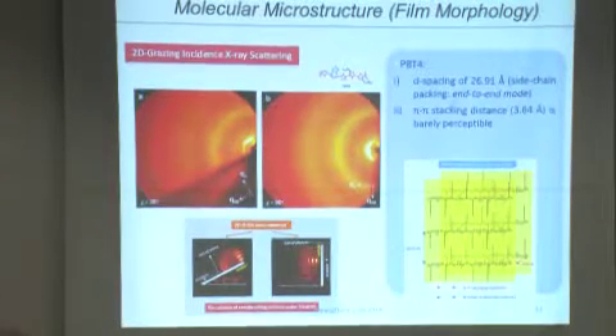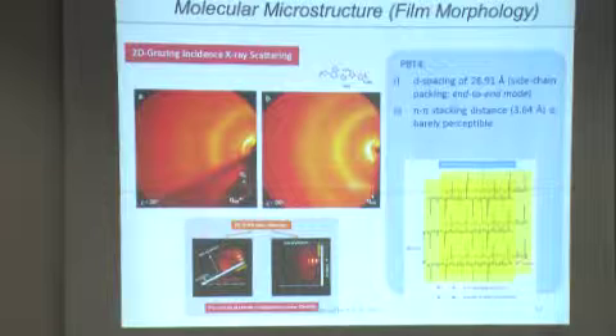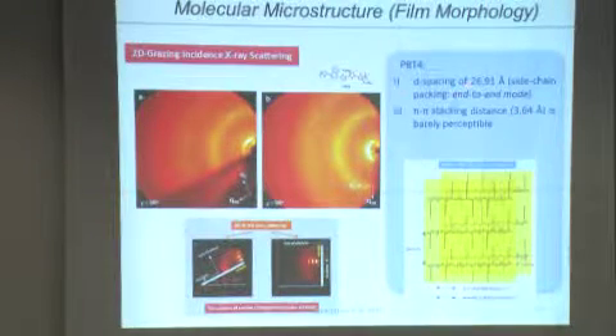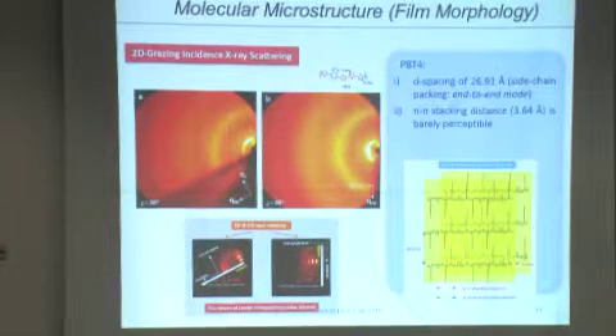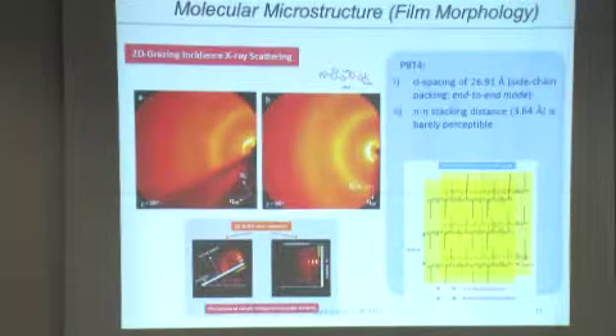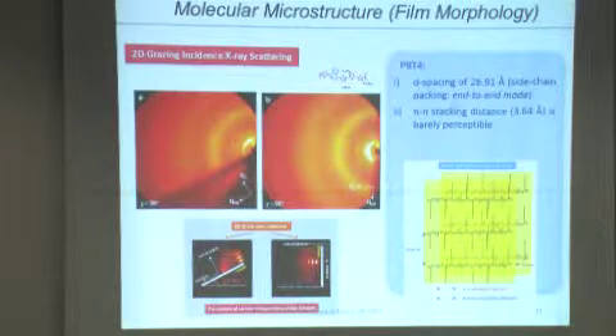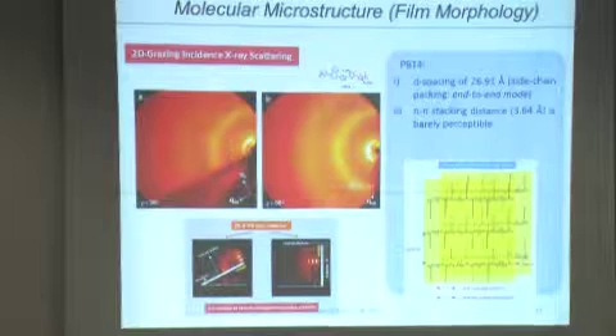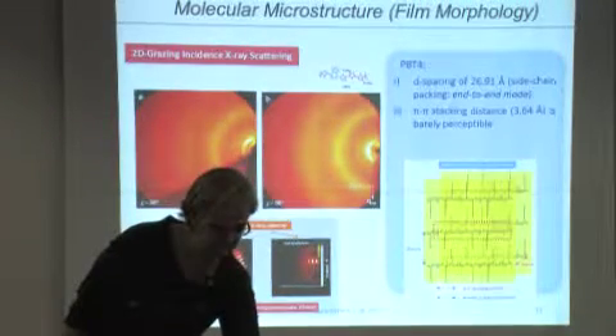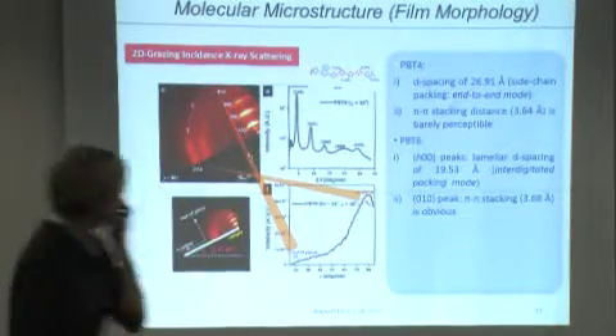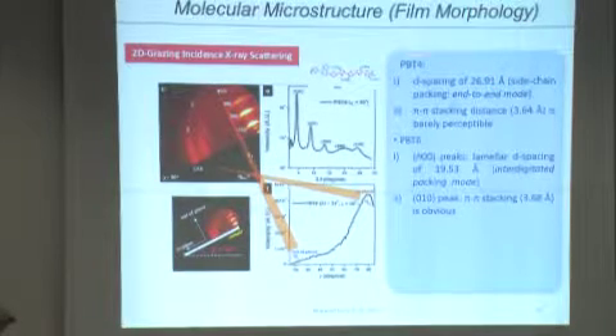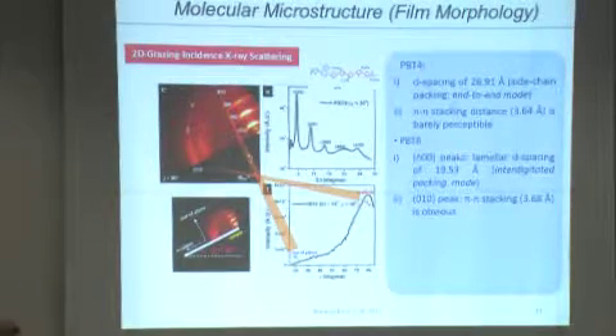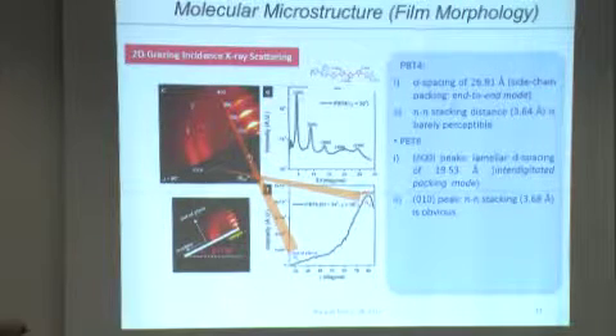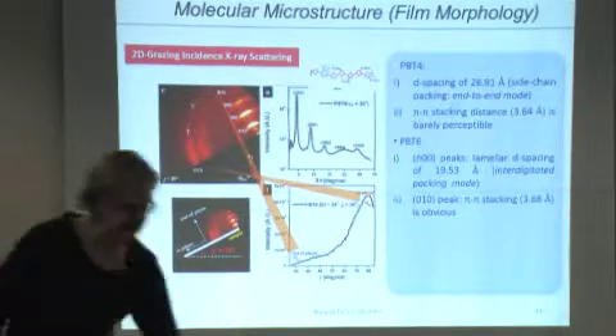The films themselves are fairly highly crystalline. There's a d-spacing of almost 27 angstroms, which indicates that the side chain packing is in an end-to-end mode, and the pi-pi stacking distance is a little over 3.6 angstroms. And that's for a 4-thiophene unit, and then the d-spacing goes down for the 6-thiophene material with pi-pi stacking at about the same level.